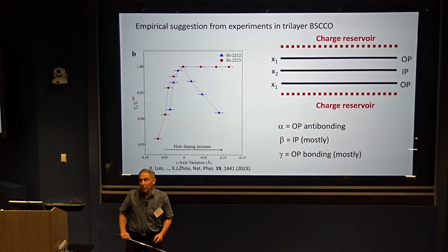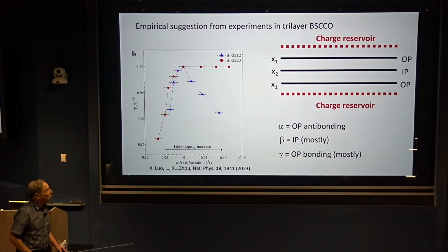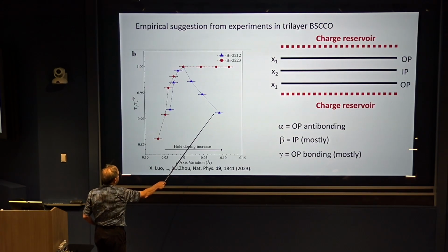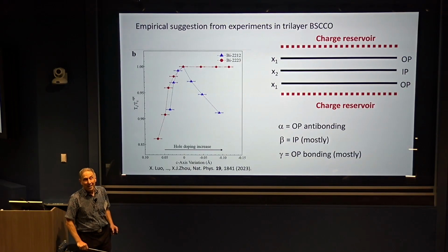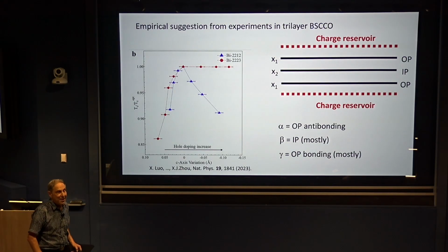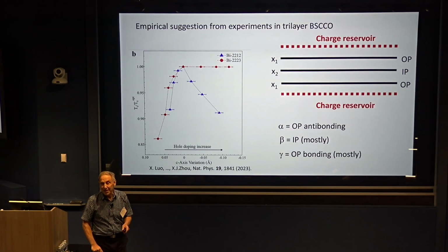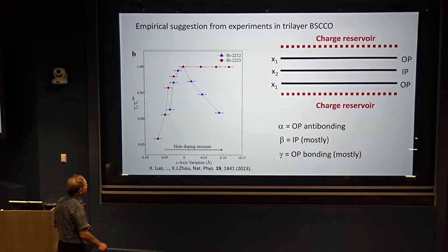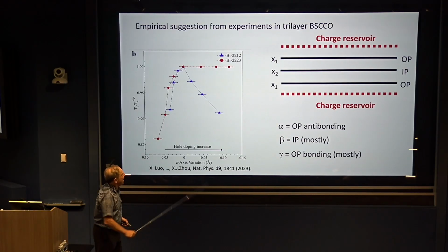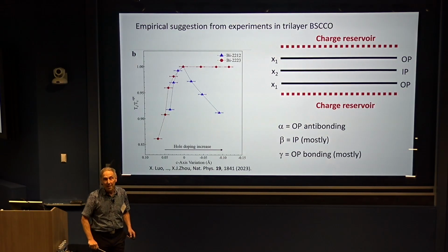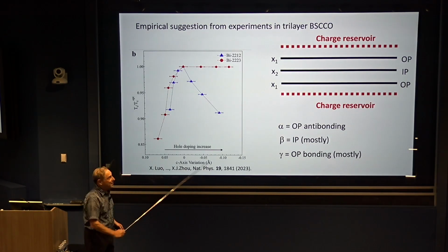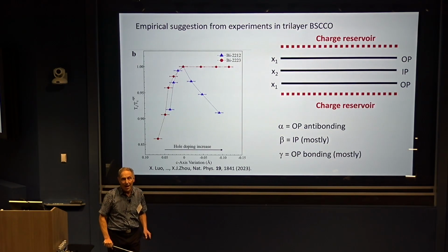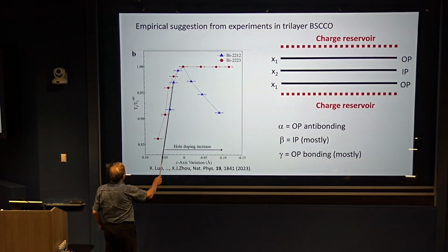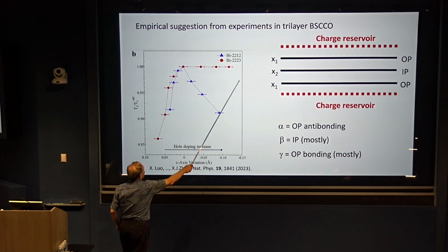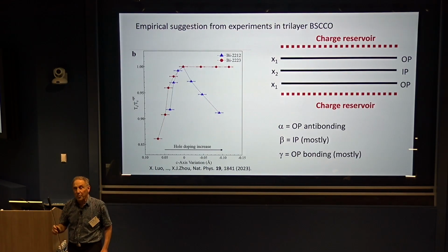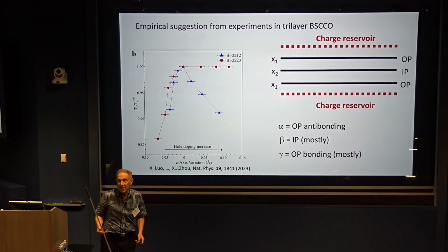There's another peculiarity of tri-layer BISCO, which is that there isn't a TC dome. So here's TC as a function of doping. Actually, rather than saying doping, which is always a little bit negotiable in these things, they plot directly the C-axis lattice constant, which is thought to vary linearly with doping. So these are all experimental curves. And here's the familiar dome for bismuth 2212. The TCs are scaled by the optimal TC, which is why they intersect here. The tri-layer BISCO has a higher optimal TC. But what you see is that the tri-layer BISCO has this peculiarity. The TC rises to optimal and then stays almost constant as you move into the overdoped region. And that's a notable thing that we would like to understand as well.